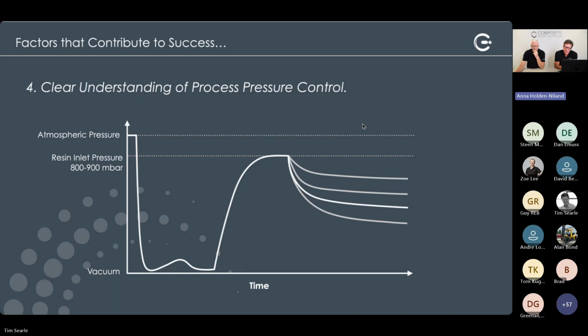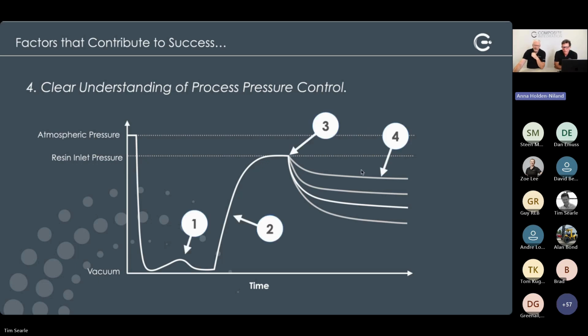This is closer to what we would find in an aerospace infusion, this particular graph, with a single component, really low viscosity resin system. But let's just have a quick look at some of the key characteristics. The first thing that we usually notice is a classical drying bump as the pressure rises. This is as we will have applied temperature to the part. So we've done a vacuum check, we've now heated the part up, and as it heats up we see the vapors start to move away, and we get a short rise in pressure before it returns to something a little bit lower.